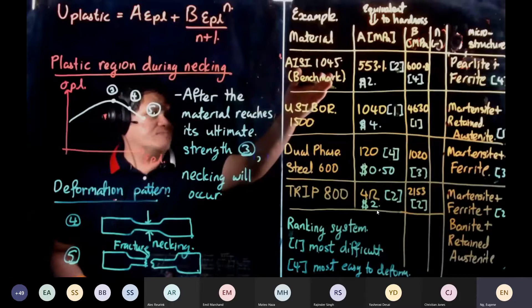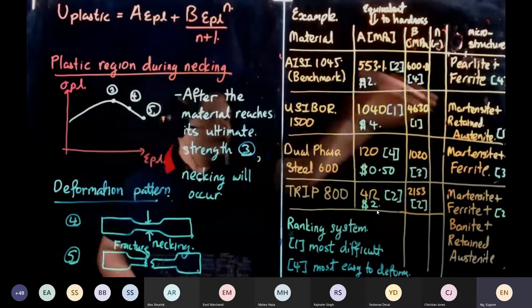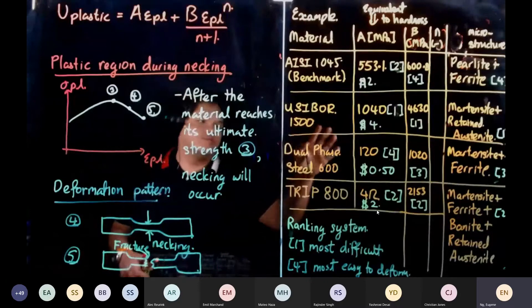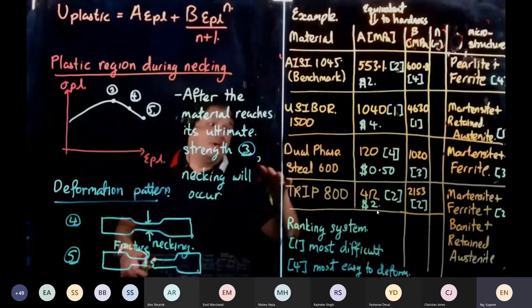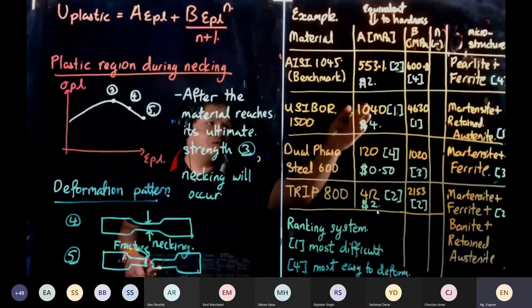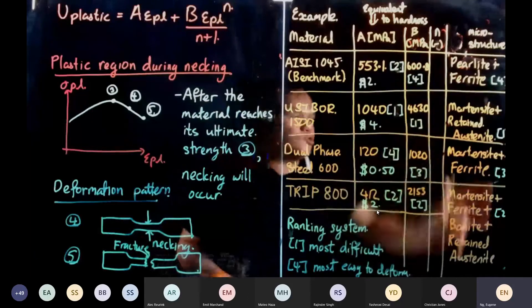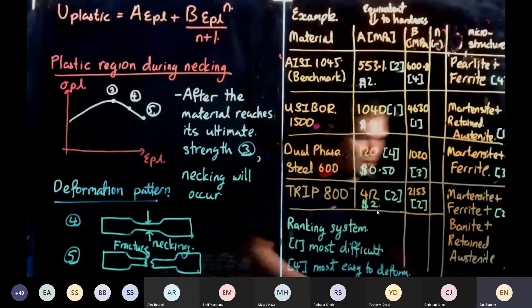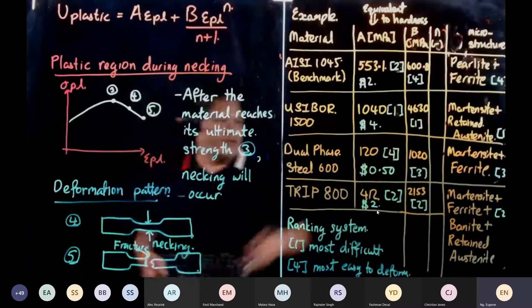Can you see what is going on? Your b and n values are more affected by microstructure than your hardness. This is my first time ranking microstructure this way, and by looking at b and the microstructure, the ranking is the same. That throws hardness into the toilet — looking at hardness alone is absolutely useless for manufacturing.